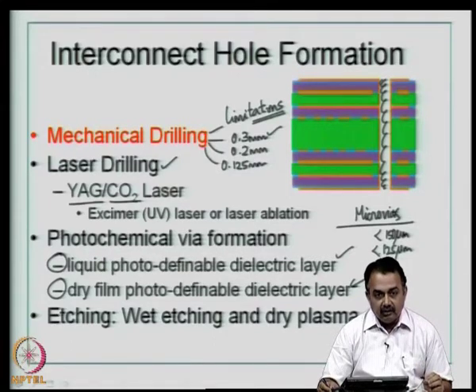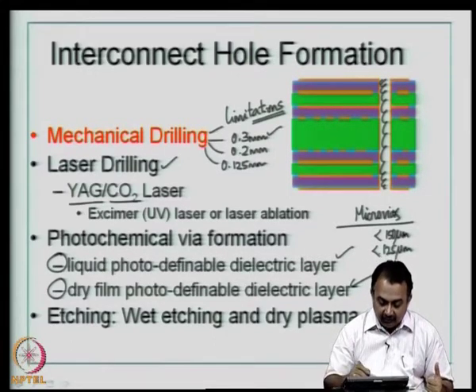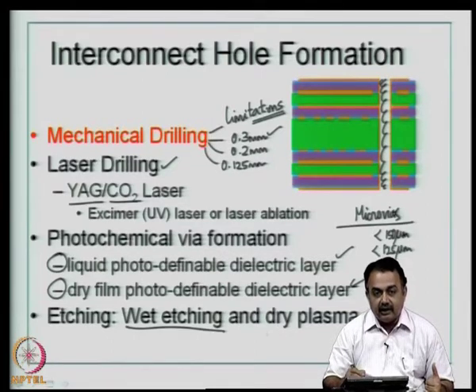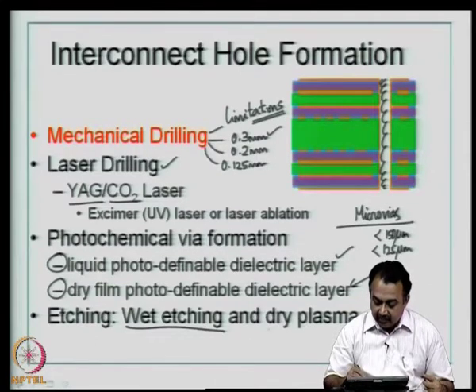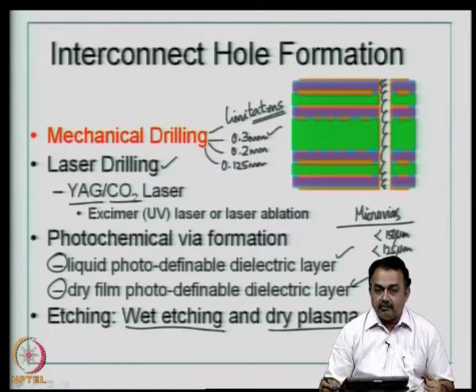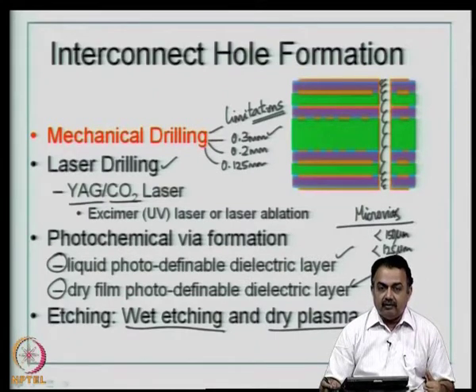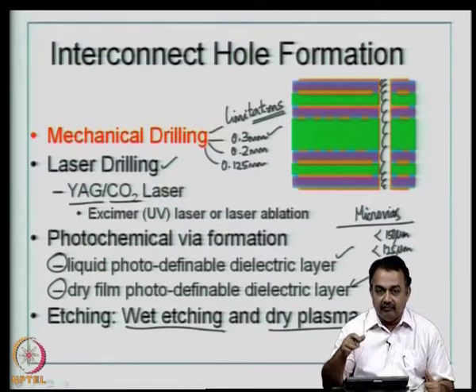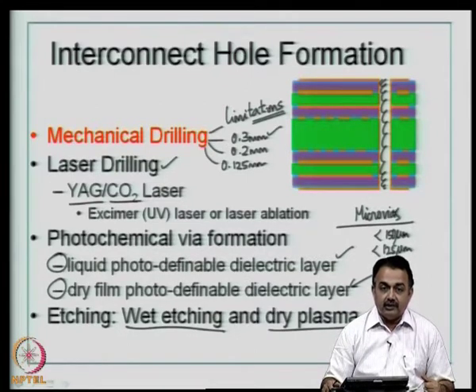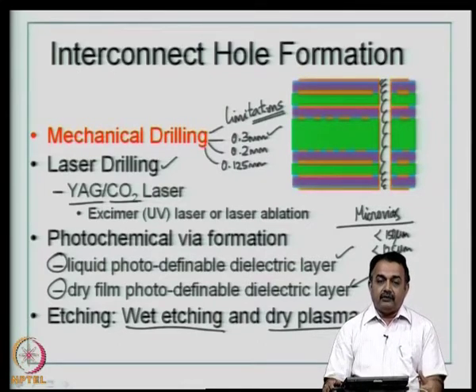There is another method called wet etching, but it does not produce the kind of results that we expect for these kind of high density interconnect structures. Using a dry plasma etch has been tried in prototyping. It produces better results in terms of the hole wall definition and the kind of undercut. When you talk about etching, there is always a problem with undercut, and wet etching produces high undercut compared to a dry plasma etch, but it is a very slow process.